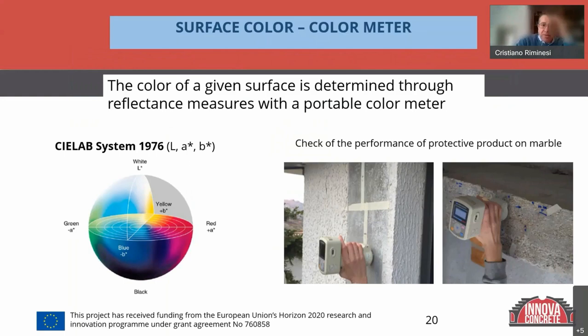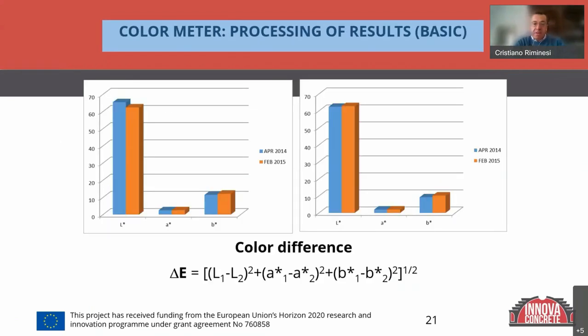For the control of the changing of color on the surface, we can use this portable device. This is the color meter. We can apply it in contact with the surface and take the reflected light from the surface by a standard light. So we can describe this reflected light in a particular three-dimensional space called the CIELAB system. And we can monitor the change of color during time, step by step.